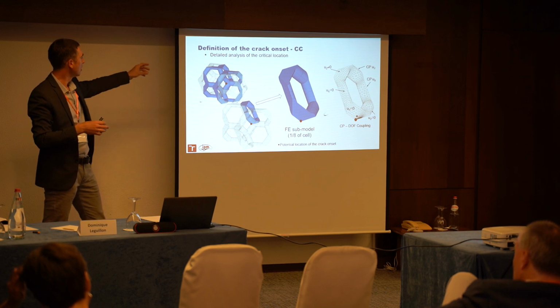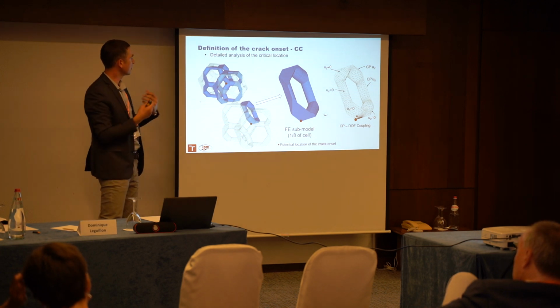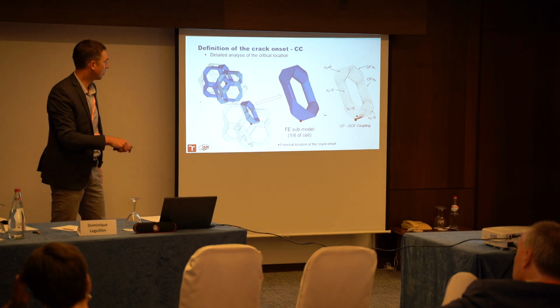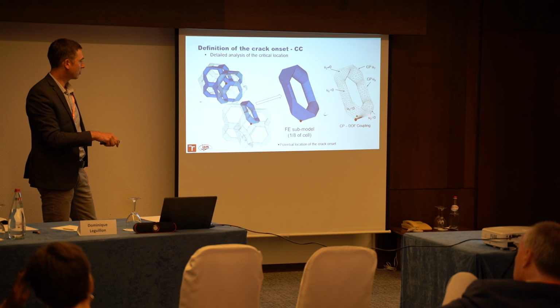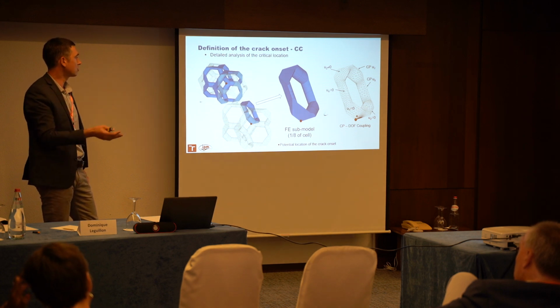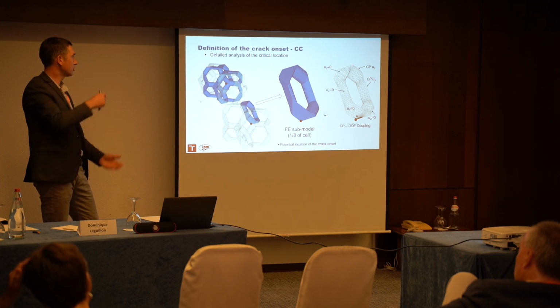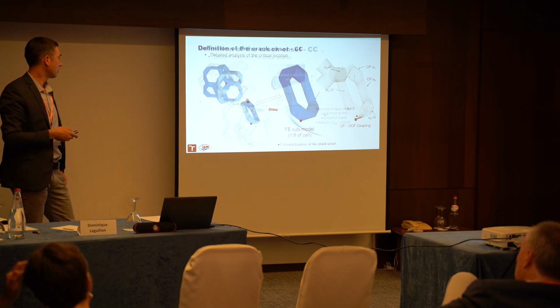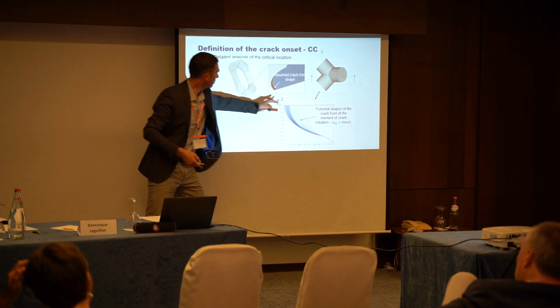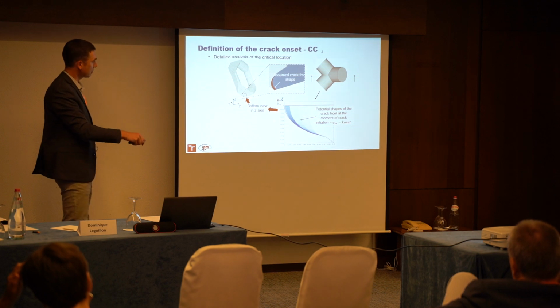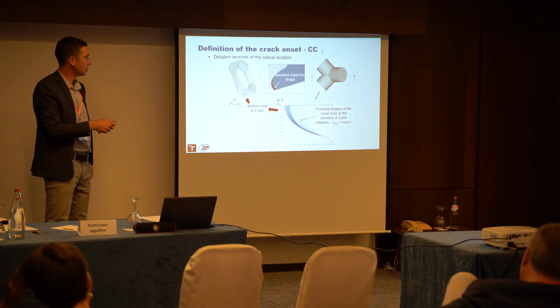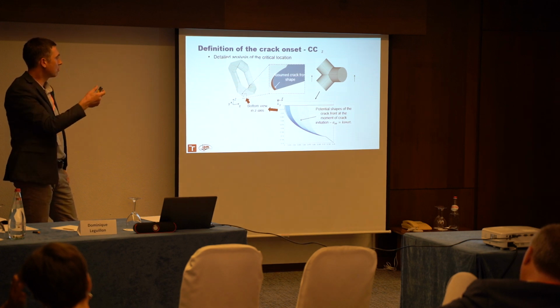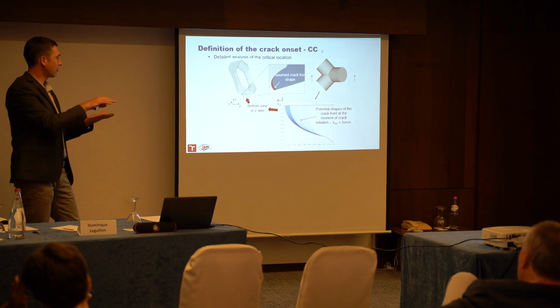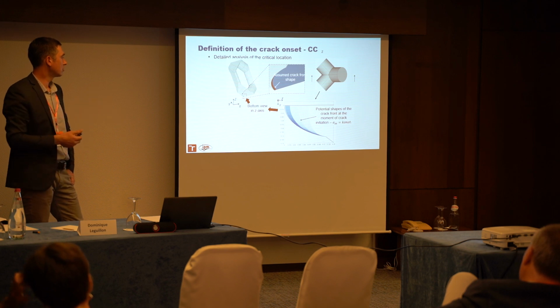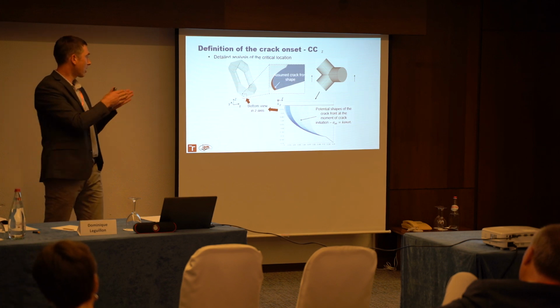We selected just 1/8 of the model where two cells are connected, and here we model the real shape of the crack defined by the stress isolines which are there upon the mechanical loading. So these are the stress isolines. This is the outer shape of the crack, and these are the stress isolines defining the crack shape. So we can have for every crack length A or crack size A specific surface of the crack faces, and we can calculate the change in potential energy caused by this crack increase.